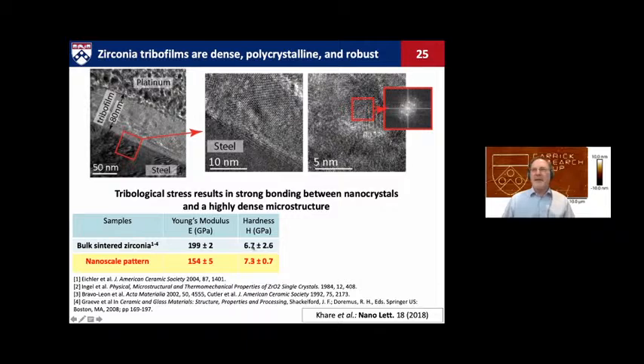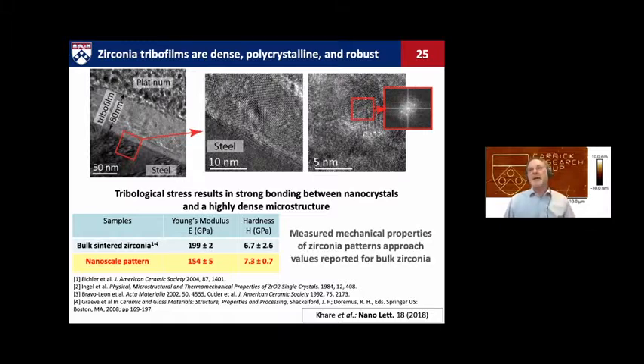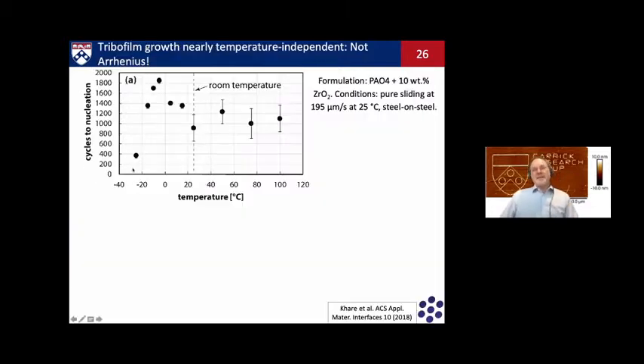So that demonstrates that the densification of this film is quite effective. So that tells us, tribological stresses can be very effective at densifying and bonding materials together. Right? Interestingly, we do not see a thermally activated mechanism. When we vary the temperature, we see initially at low temperatures, we can actually grow these films at low temperatures, unlike ZDDP. You can even grow them at minus 30 degrees. A rapid growth with temperature, but then just sort of fluctuations as we change.